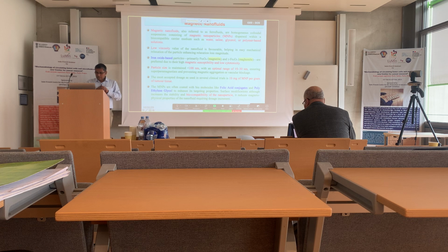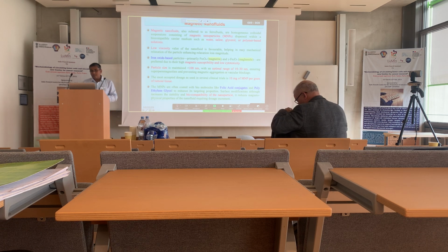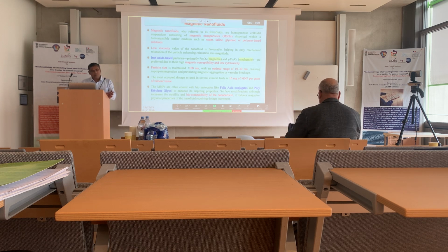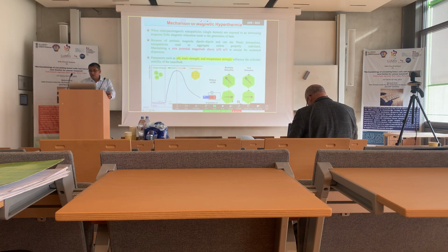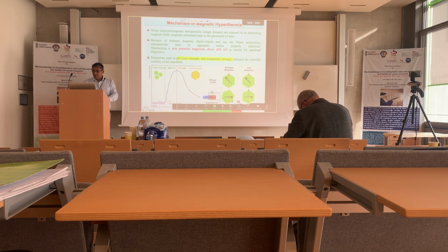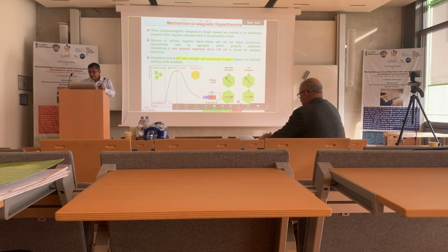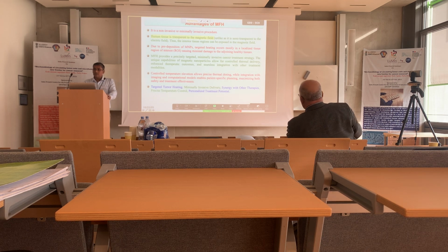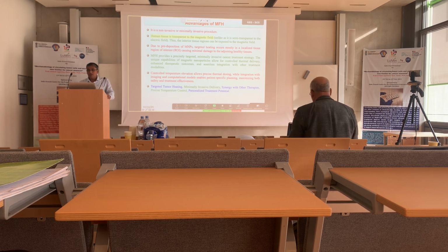Sometimes for targeted tumor therapy, folic acid conjugates and polyethylene glycol conjugate coating of magnetic nanoparticles are good for magnetic fluid hyperthermia therapy, and even some surface modification of the nanoparticle gives quite a good response. Of course, with and without the presence of an alternating current magnetic field, there are different responses of the tumor. So we have gone through several numerical tests of nanoparticle distribution, and also the frequency level and the intensity of the magnetic field, to get the essence about the correct domain of the magnetic fluid hyperthermia test.